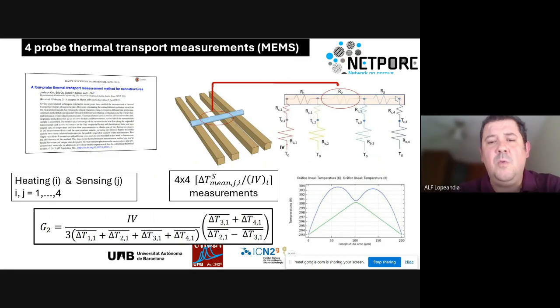The fact is, from here we will extract 16 measurements and 16 equations. In fact, this is just Kirchhoff equations. We can treat them as Kirchhoff equations, and we can extrapolate G2 directly, getting rid of the thermal contact resistance. This is a very clever configuration that Lishi arrived with, and this permits us to remove the thermal contact resistance. I say 16 measurements because we measure the wire that is heated up, and we measure the 3 other wires. We have 4 measurements when we heat wire 1, but we have to heat wire 2 and measure the other 3, heat wire 3 and measure the other 3, and heat wire 4 and measure the other 3.